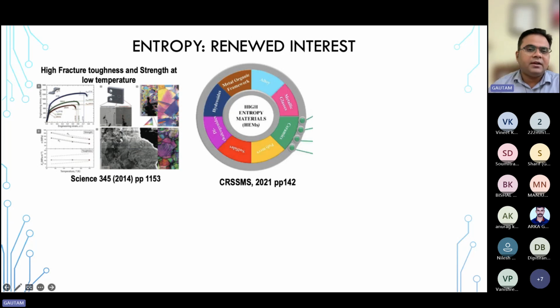So what was happening here? They showed that the fracture toughness was basically increasing because at the crack tip, nano twinning was taking place, which was bridging the crack, and it was not allowing the crack to grow. So that was something, and many papers basically came out in this area, talking about this kind of phenomenon. They have again published a paper. They have done some work recently, last year, where they have taken this to liquid helium temperature and shown great fracture toughness there also.